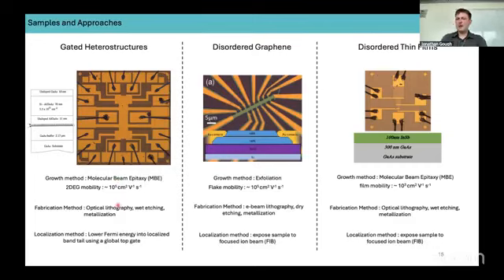So this has advantages and disadvantages. One disadvantage is you're limited by leakage resistance to the top gate. And in a heterostructure, you're also limited by things like parallel conduction. So these samples are extremely resistive, typically 10 to the 12 or even 10 to the 11 ohms. So these small effects that you would typically ignore in 2D systems start to affect your measurements.